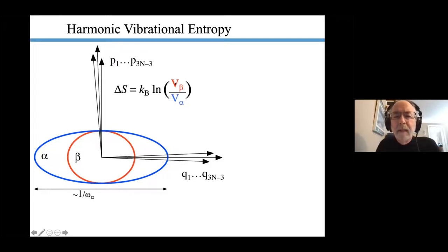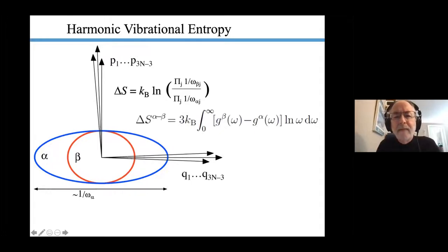And these are all looking simple here as I show it like this, but actually there's Avogadro's number of degrees of freedom and normal modes in the system. So that's pretty complicated. We really have to take a product of this total volume for all of these frequencies, which means we need to know basically all of the frequencies. But the log of these products is the sum of logs, and we can write this out as an integral for a continuous function, the density of states. And the difference in vibrational entropy between these two crystal structures would be just their differences in normalized phonon densities of states weighted against the log of frequencies, times 3kB for three dimensions. And this is the correct result for high temperatures.